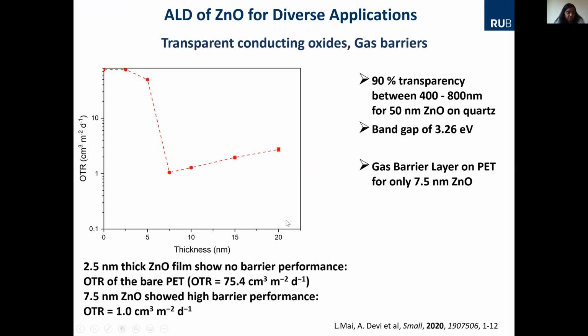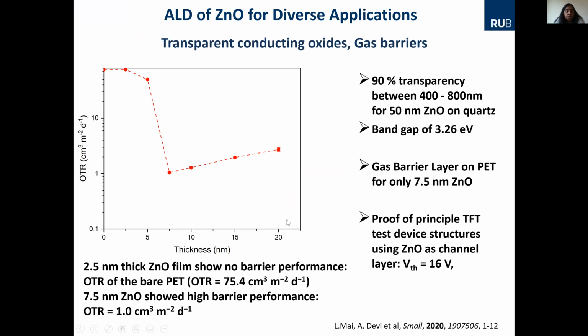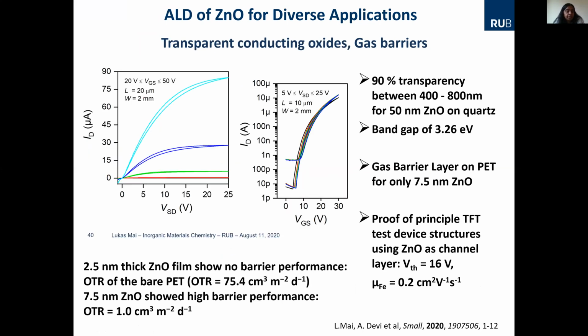permeates, as a function of thickness. Then we also tried, or the engineers tried, to see whether we can build up some TFT structures with zinc oxide channel material. And again, the transfer characteristics, for example the IV characteristics, were measured, and you see in this case the threshold voltage around 16 volts, as well as the field effect mobility around 0.2 centimeters squared per volt second.